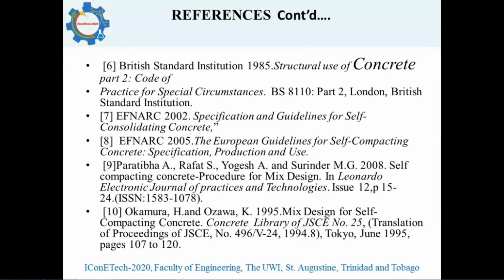When you replace cement with GSA, how did you adjust the volume? Actually, the SCM, which is supplementary cementitious material, was used. There was a table for the materials that I displayed. The component materials were measured by weight, so it was batching by weight. So like now, at 10%, the cement was 510 kilograms per cubic meter. So the 10% of it is removed from the cement, and then the same amount in weight was replaced back to make up the total weight of 510 that is used as the proposed design.